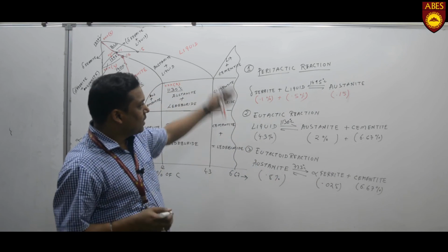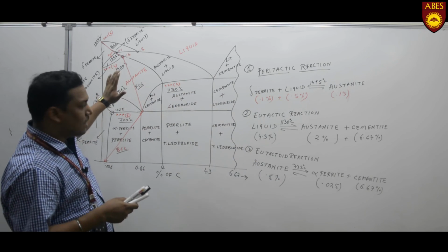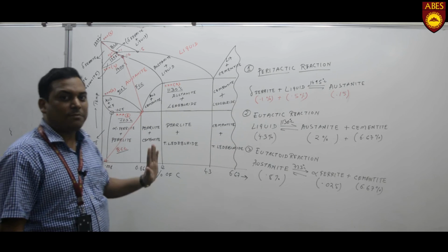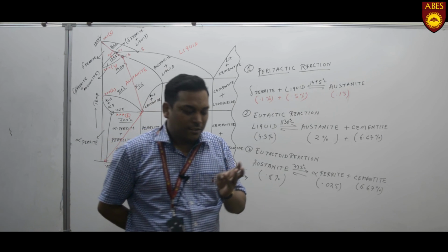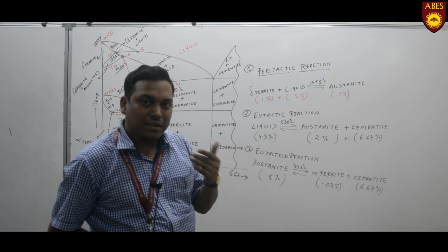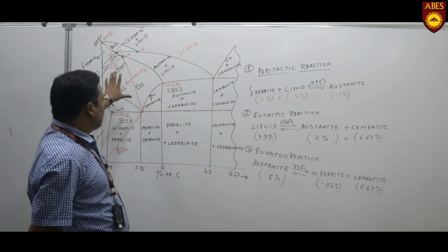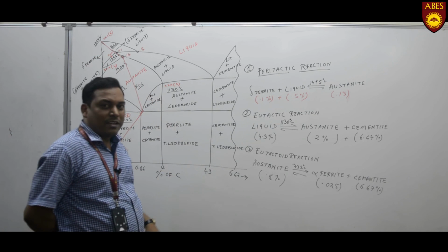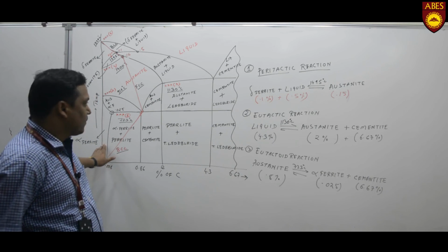The summary of this iron carbon diagram is that there are three types of structure: first BCC, then FCC, and then again BCC. There are six key temperatures: 723, 910, 1130, 1400, 1495 and 1539 degrees centigrade. Above 1539 degrees centigrade the iron melts. The main phases are austenite, delta ferrite and alpha ferrite. Austenite is also called gamma iron, and alpha ferrite is basically a pure form of iron.